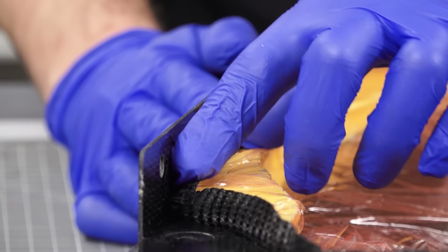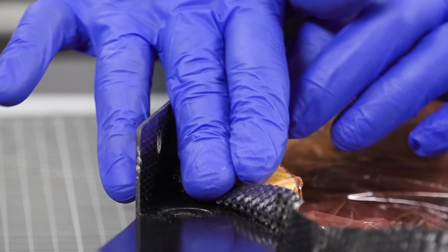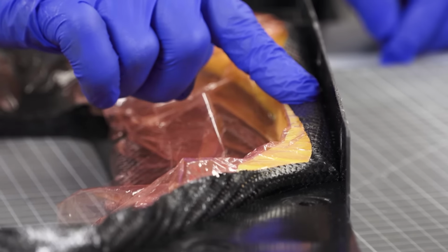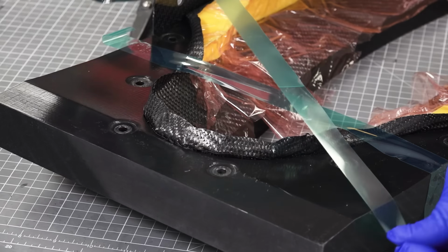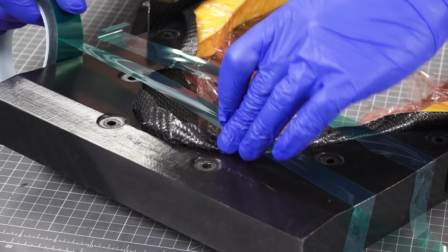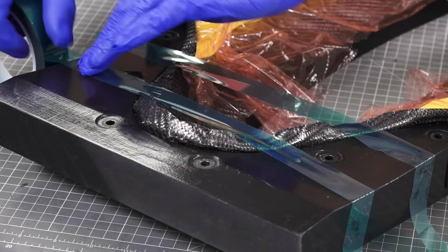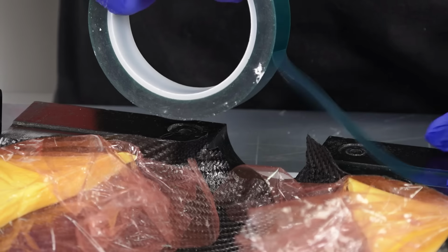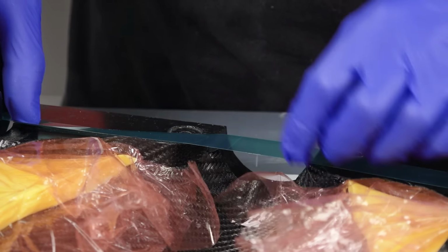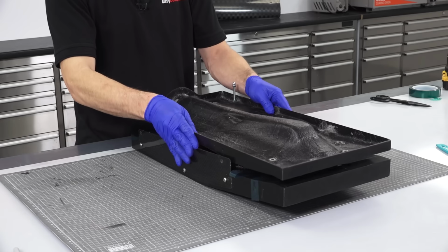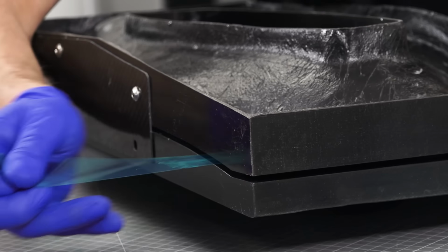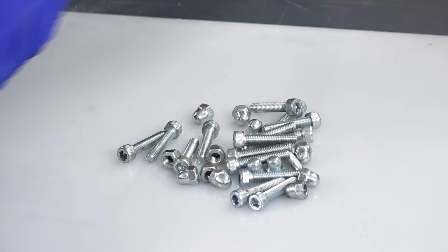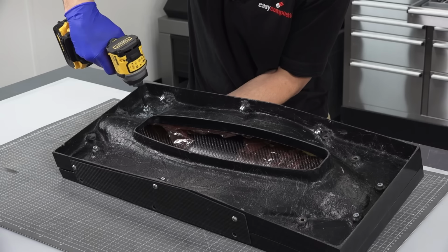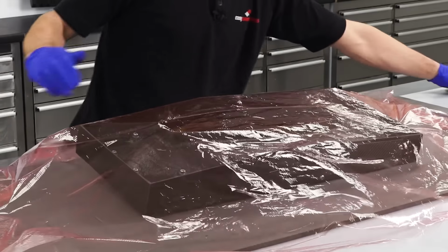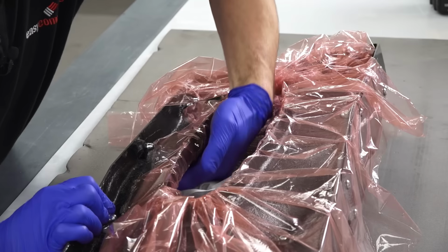The rest of the laps are then folded into approximate position, and you can now see quite clearly how these laps are going to work to connect the pieces. A neat little trick to holding the laps in position is to use some flash release tape across the mould to keep them folded down. This reduces the risk of the carbon fibre folding the wrong way during closure and becoming trapped in the flange. When the moulds are initially closed, the tape can then be pulled out, leaving the laps in the right place. After clamping down, the prepreg is then completely covered in unperforated release film and secured in place with flash release tape.